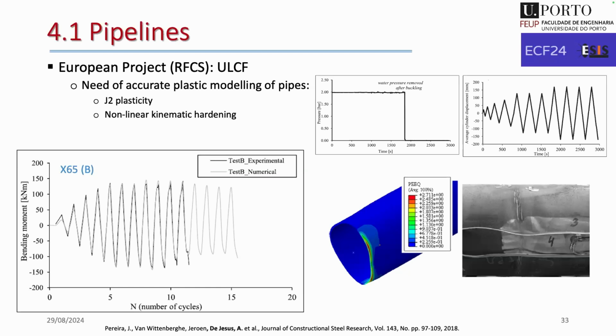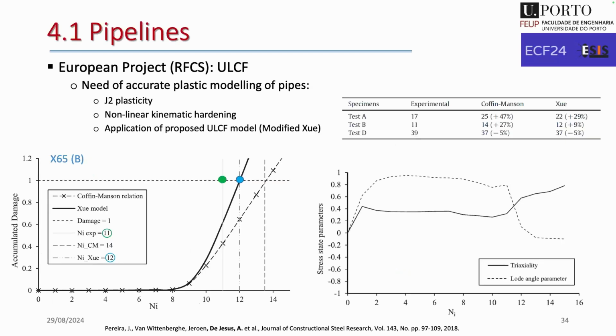But as I told you, we need to first model very precisely the elastoplastic behavior of the pipe. And the most important is to capture the plastic instability, because as soon as you get the plastic instability, your triaxiality will increase and the Lode angle parameter will decrease. All of this will result in the reduction of the material ductility. So that will speed up the failure of your material. So we were able to improve the predictions regarding the overestimation of the Coffin-Manson approach.